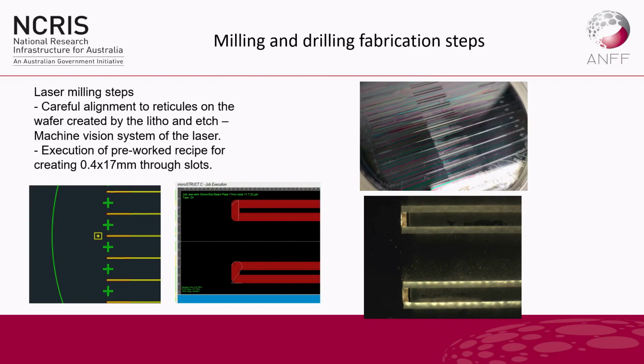It's a very, very expensive, very hard process to do with chemical etching. Okay, it's a very long Bosch process to eat out that much silicon. But because the use is not there to be particularly clean or anything, it's just there to create a separated bridge of silicon, the laser has been the ideal tool for machining these out.